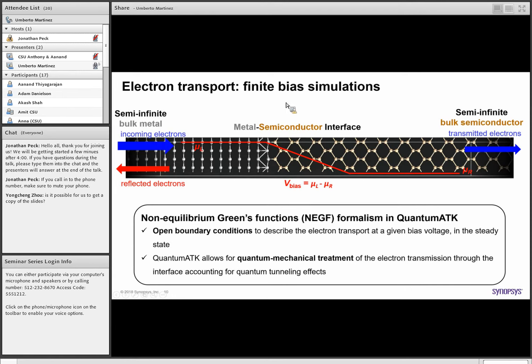We can then inject electrons. This will be the picture, and because we can apply a finite bias, so change the chemical potential of the left and right electrodes, some electrons are transmitted and some are reflected. And basically, by calculating the transmission spectrum, we can then calculate the current. Within this formalism, especially if we use DFT, a key feature is that by studying this electron transmission through the interface, we can actually account for tunneling effects. So electrons can go from left to right and propagate by tunneling or thermionic emission and so on.